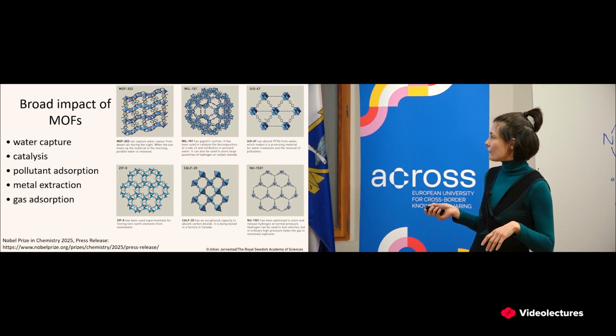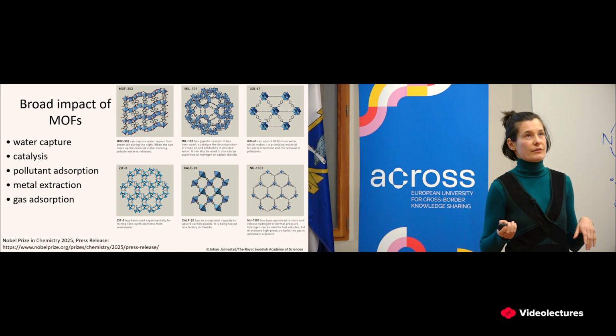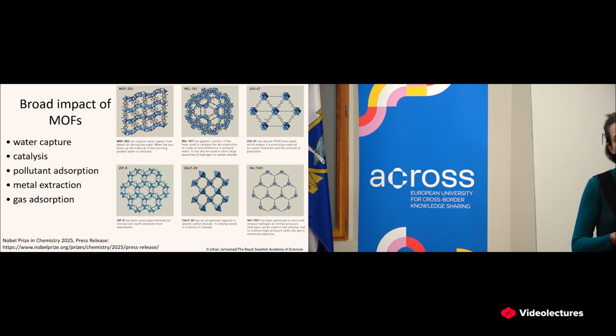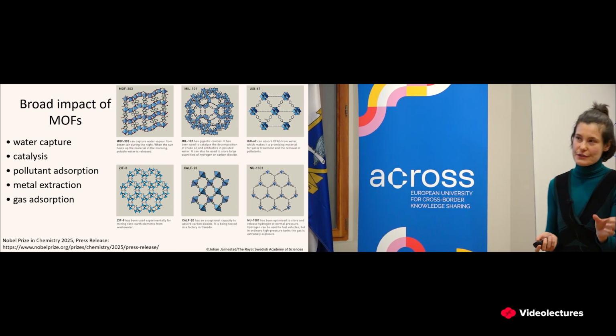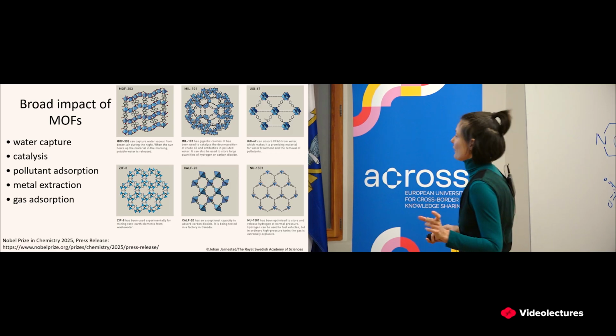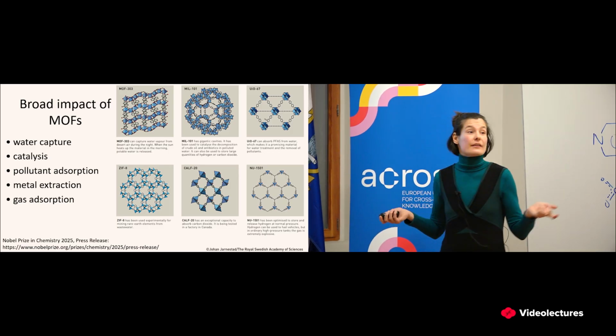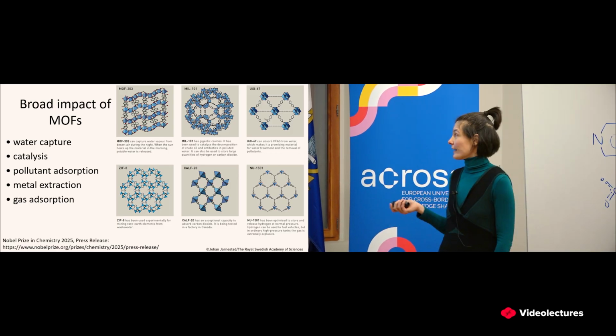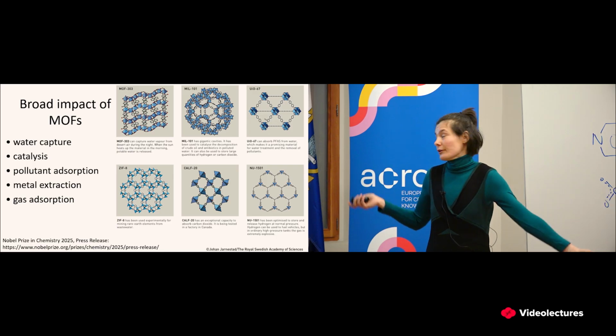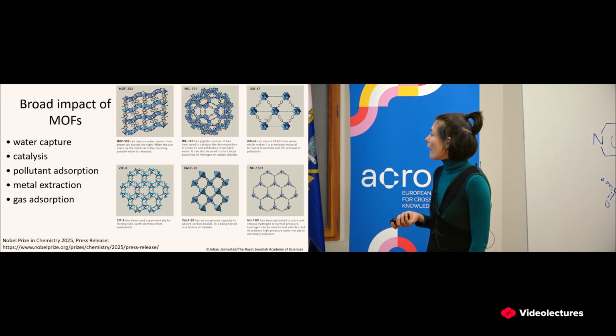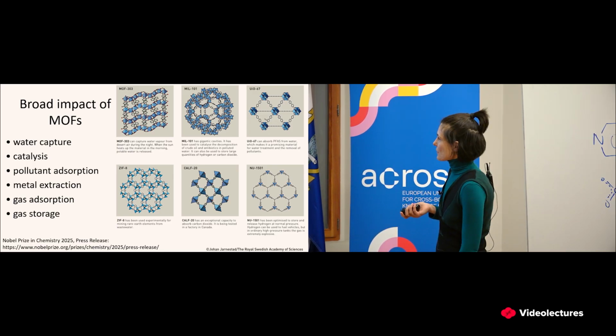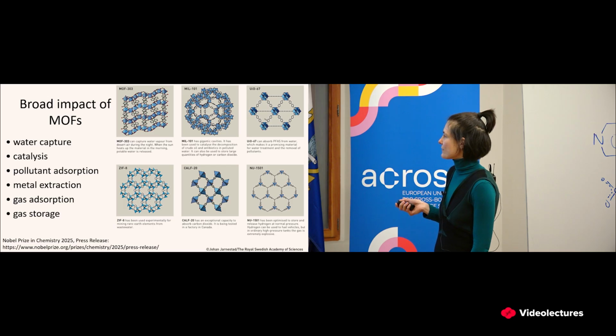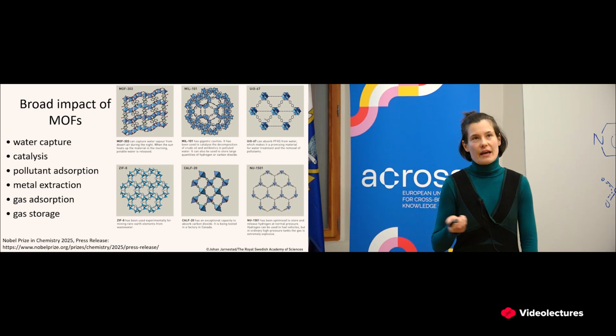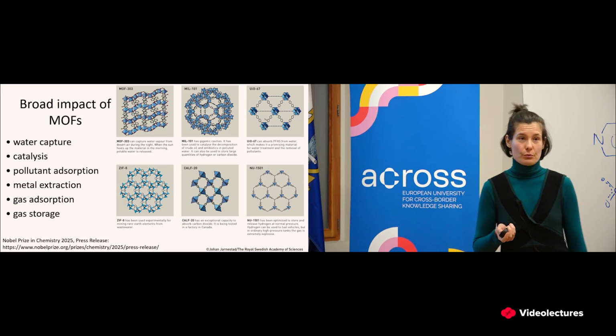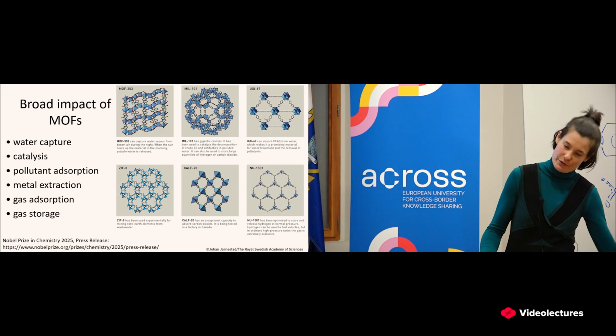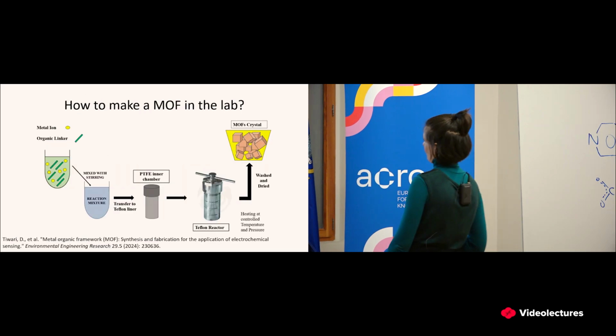And then this one is used for CO2 adsorption. It supposedly has pore dimensions that fit the CO2 molecule directly, and it is apparently even being tested in some factory in Canada for industrial level applications. Gas storage, I believe I have mentioned. This one was tested for hydrogen gas storage. Mostly MOFs work well for hydrogen storage at low temperatures, unfortunately not at room temperature.